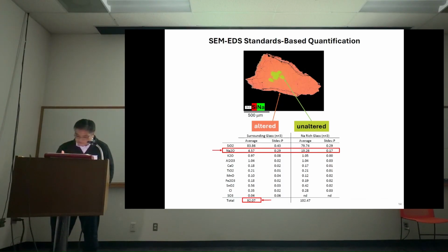Everything else is 1% or below, so there's only sodium and silica in this glass. In my training in ceramics, you can actually buy dispersants called sodium silicate. That's how dispersants basically work, by dissolving in water and suspending your clay raw materials. So if it's that prone to glass degradation in that form, it is likely not very stable.